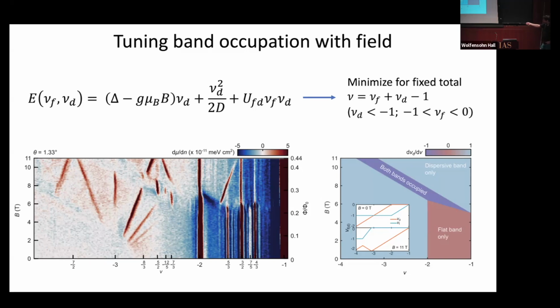Okay, so in this regime, well, I should point out that this is a theoretical calculation. In this regime here, you expect to occupy the opposite spin s-type orbital. But at some point, the Zeeman energy overcomes this energy difference, and you prefer instead to occupy the more dispersive p-type orbitals. And it's exactly there, similarly in this regime, where you tend to see the Hofstadter physics dominating. So basically what we're seeing here is a difference in the ground state.